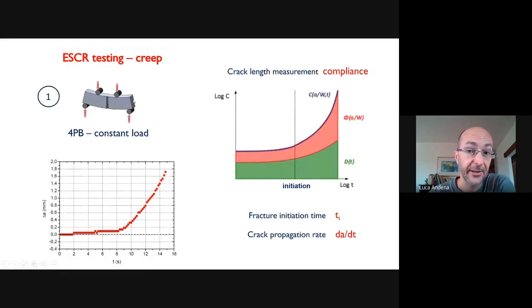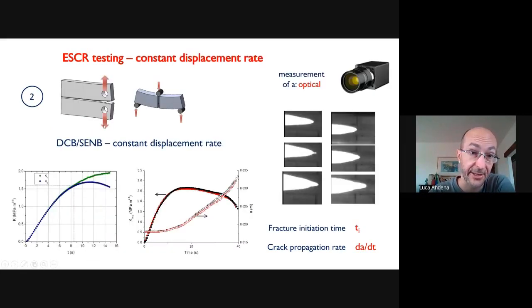And here there are different ways of measuring the parameters you need. With our setup with the creep ones, we use the compliance method to characterize the crack length. This is something you can do even when you cannot see the sample. And you know that the compliance depends on the creep compliance of the material and the function of the notch length. So by recording the compliance, you can know what the crack length is at any time, detect initiation, and then measure propagation. When you can see the sample, as for example in this case, for the constant displacement rate test, you can use an optical method to record the crack advancement, so you can get all the information you need.